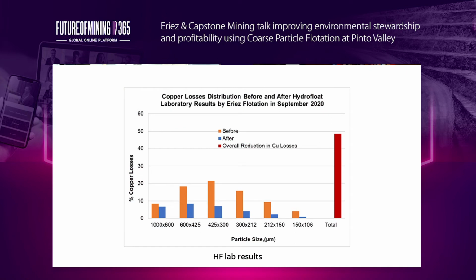The HydroFloat is a novel flotation technology that allows the flotation process to be pushed beyond the particle size range of conventional flotation technology. The grind size at Pinto Valley is very coarse at a P80 of 300 microns. It turns out that about 80% of the copper and molybdenum that are lost to tailings are in the coarse size range, shown here in orange, which makes sense because we know that conventional flotation does not work well in this range.